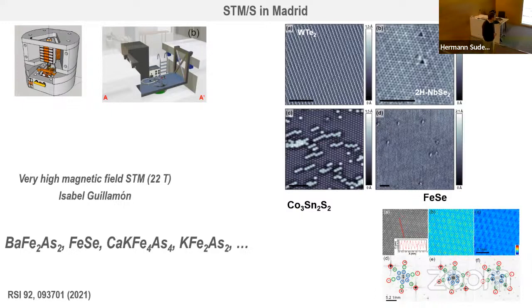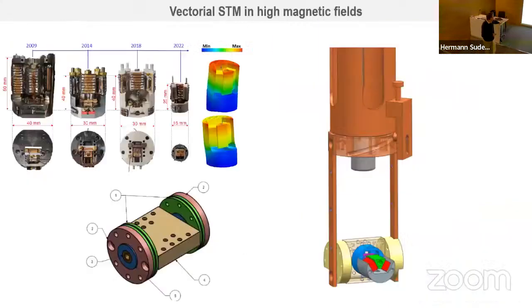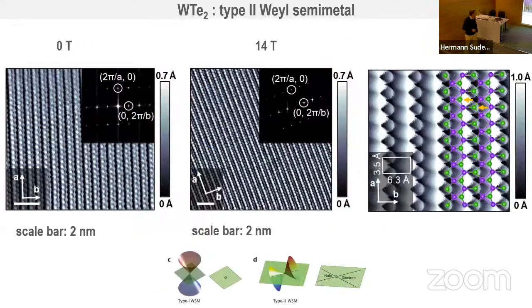Recently, there has been Isabel. She has been developing the high magnetic field activity. So she has discovered two-dimensional superconductivity in CaKFe4As4 vortices at 20 Tesla. This image is here. I made it at 20 Tesla, which is a huge magnetic field, and done a lot of things with these machines. We are also trying to see if, thanks to this, we can rotate the STM. We will see if we manage to do that or not.